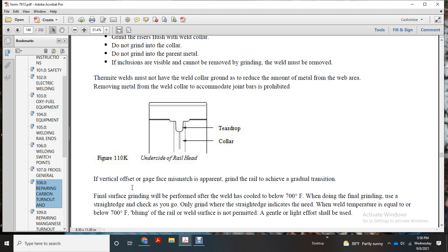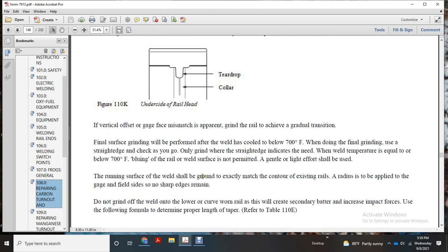When doing the final grinding, use the straight edge. Check it as you go. Use the straight edge to indicate when the weld temperature is equal to or below 700 degrees, as bluing of the rail and weld surface is not permitted. Gentle, light effort shall be used. The running surface over the weld should be ground to match the contour of the existing rails. Radius to be applied on the gauge side and field side with no sharp edges remaining. Do not grind off the weld until the lower curve, to avoid creating a secondary batter and impact forces.